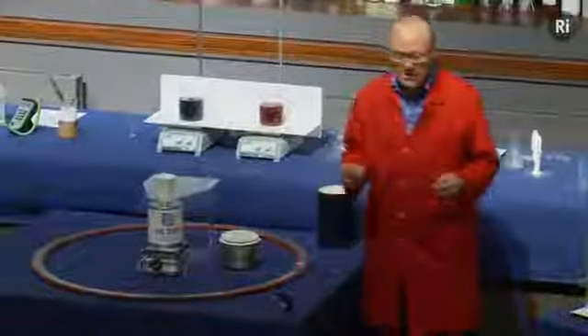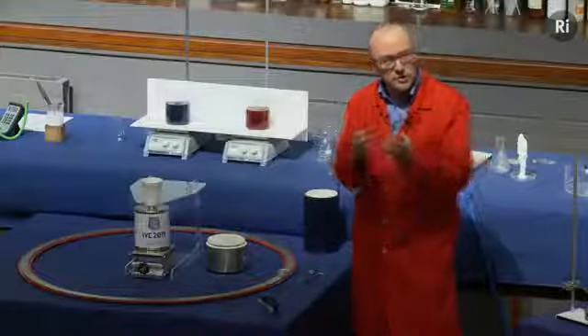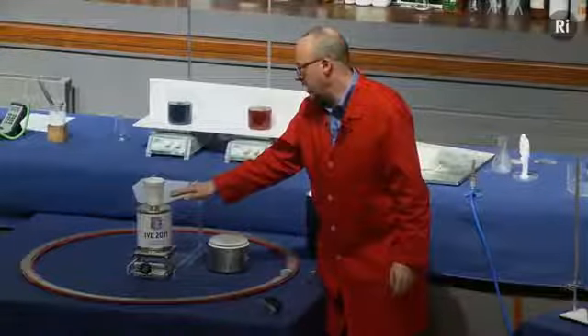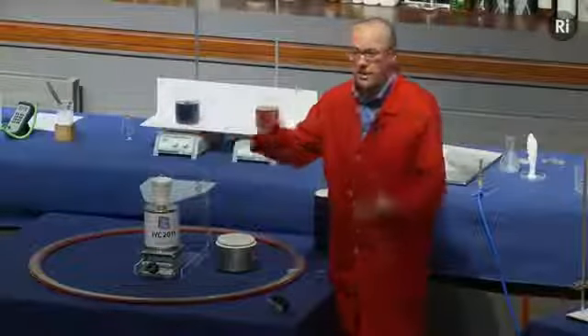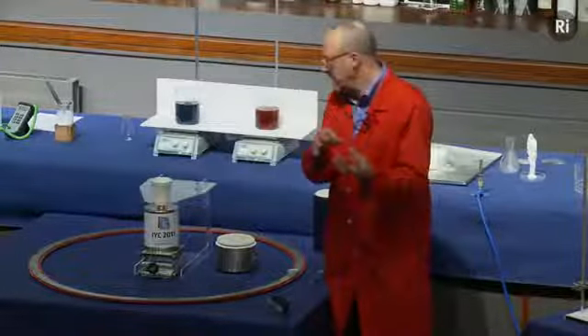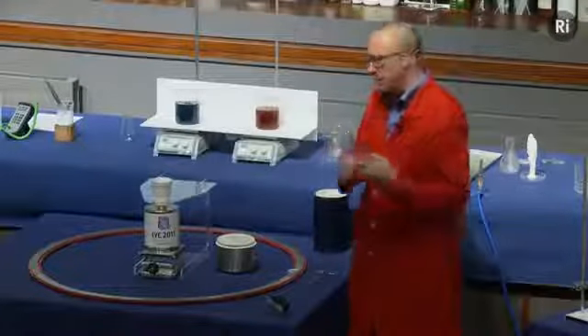This is actually quite a special kind of superconductor — it's what we call a type 2 superconductor. That means that as well as repelling magnetic field, it can also trap magnetic field. I've got another one of these sitting inside this polystyrene cup, and underneath is a cylinder with a very strong magnet on top. The field from that magnet was already passing through the ceramic material before I added the liquid nitrogen. Now that I've cooled it down, it should have become a superconductor and hopefully it will have trapped that magnetic field, so it should still be gripping onto that field.